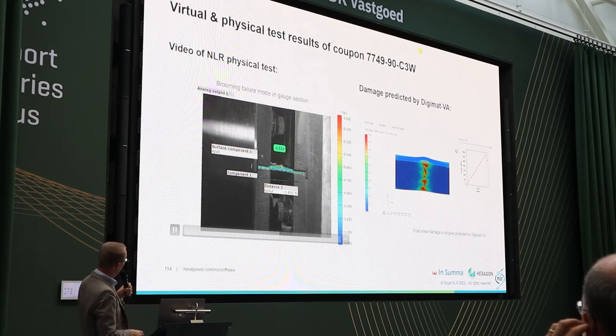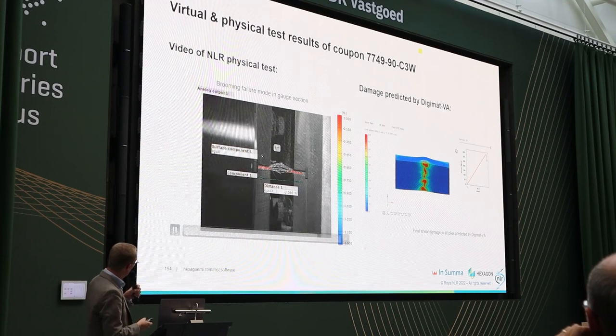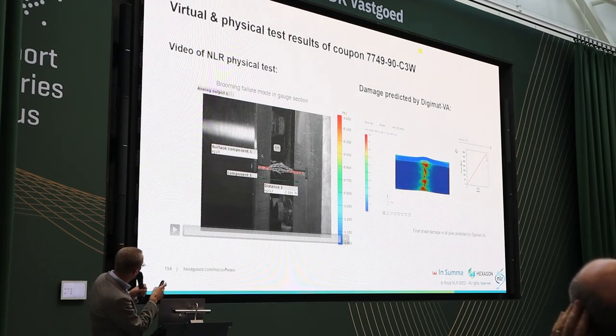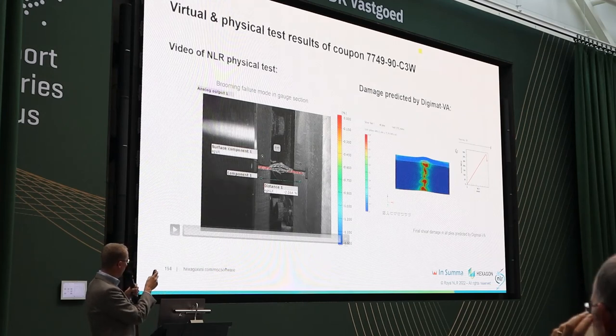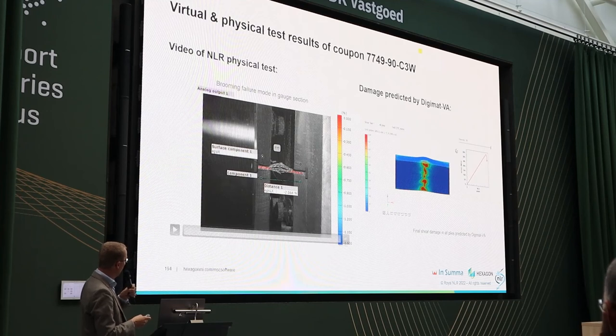And on the right, you see one of the simulations in Digimat with the waviness taken into account. The area of the damage is quite well predicted. This variable is the shear damage, and matrix damage has the same kind of damage pattern, and delaminations and fiber damage are also occurring.